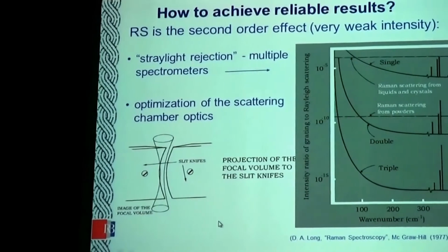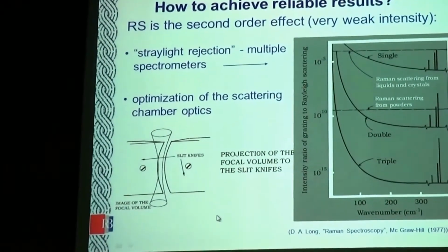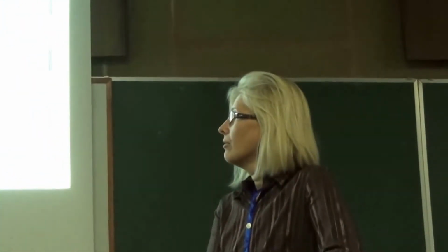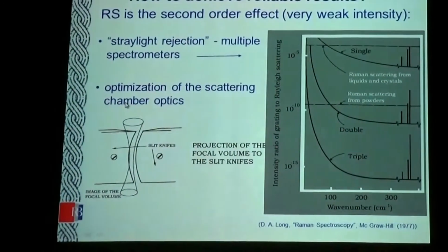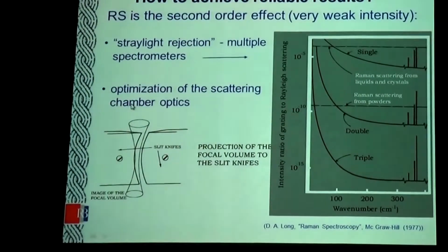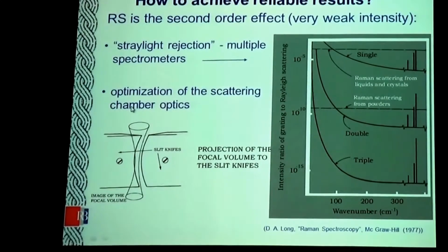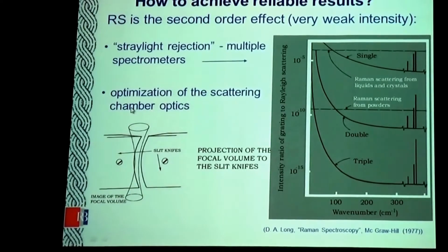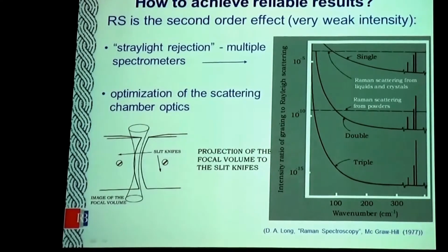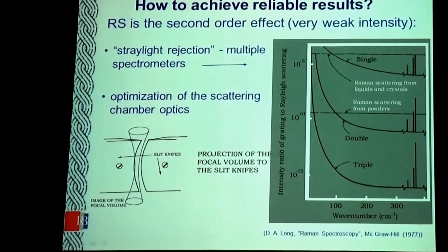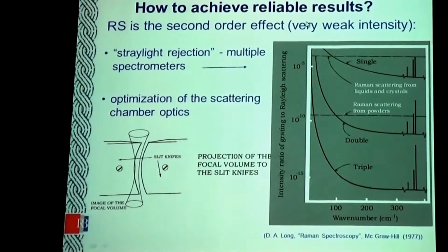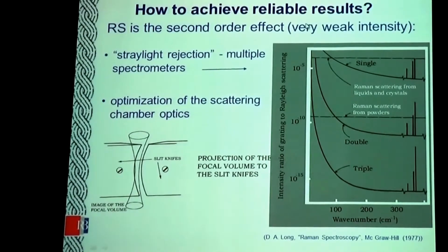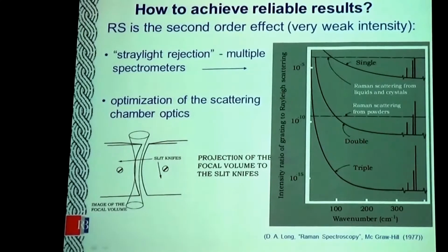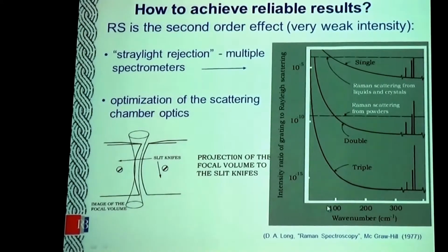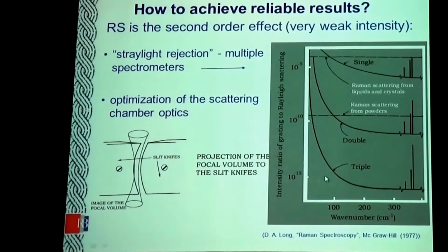But I would like to also stress some things which we should take care about during our measurements. We should optimize the scattering chamber optics, because the Raman scattering is even 10,000 times lower in intensity than Rayleigh light. This is the reason we always have a Rayleigh line. So we should cut the wings of this Rayleigh light to get the Raman scattering signal, especially if we would like to see very low wave numbers.